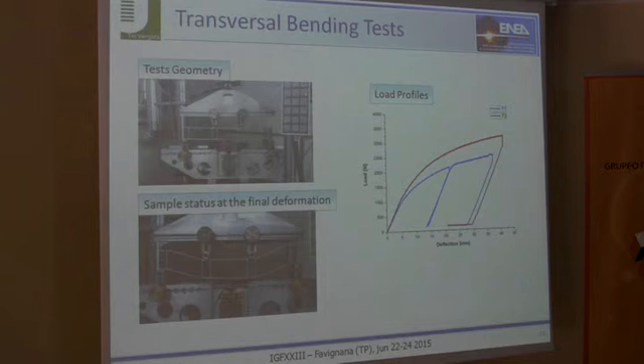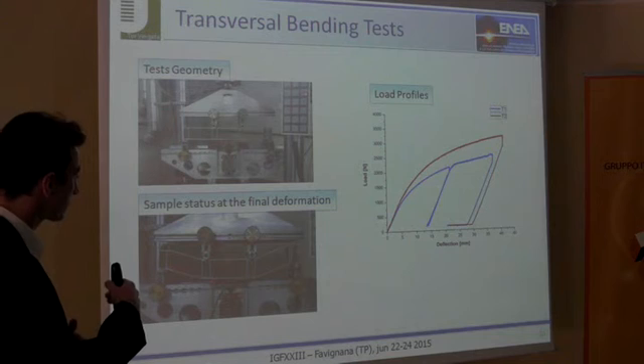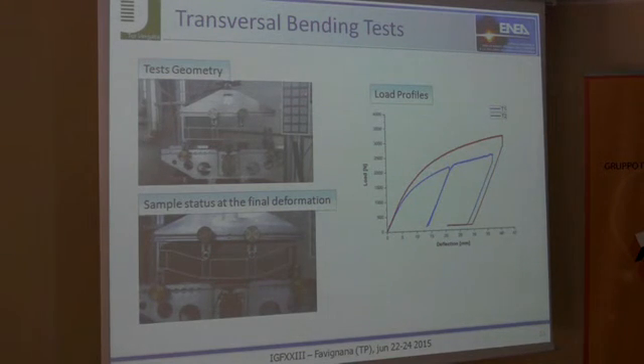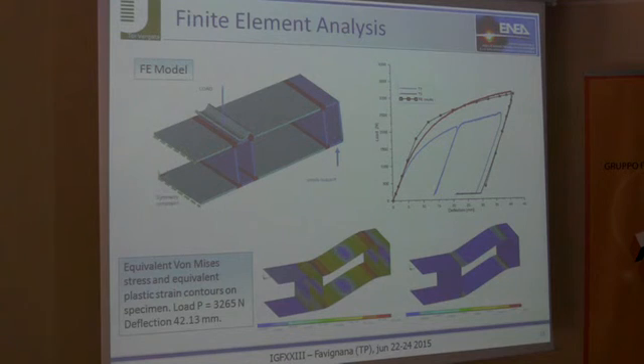strain. In the transversal bending test, you can see the test geometry and the load profiles. The load value is very low compared to the longitudinal bending test because the sheets are not connected together and operate in an independent way. But the test confirmed the good behavior of the welds and the ductility of the welds. And like the longitudinal bending test, the finite element analysis confirms the results, and you can see the equivalent von Mises stress and the equivalent plastic strain.